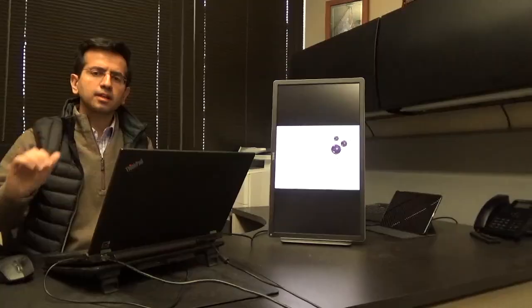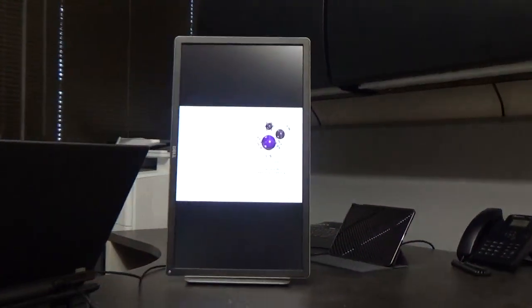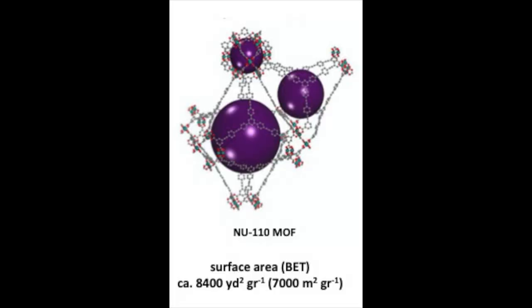This is one of the metal organic frameworks made at Northwestern University, known as NU-110, and the surface area of this MOF is 7,000 square meters per gram. And just to show you what it means in an actual comparison and analogy, one gram of just this metal organic framework has a higher surface area than an entire football field.